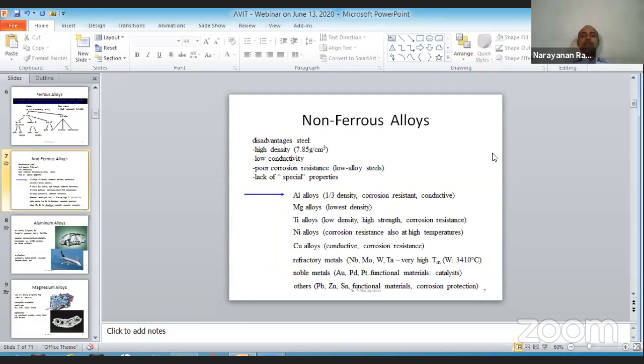I told you about other alloys. People use titanium. Titanium is very good. Titanium is extremely corrosion resistant and it has a low density. So compared to stainless steel, it has only 40 to 50% of this. So this is a much lower weight material. It has high strength. It has very good corrosion resistance. But the problem with titanium is when it is placed inside the body, it has poor frictional characteristics. That means it tends to rub more. Compared to stainless steels, titanium tends to rub more and can cause friction. When it is placed inside the body, when there is a metal to metal contact, then titanium will give very poor frictional performance. So this is one major problem with titanium.